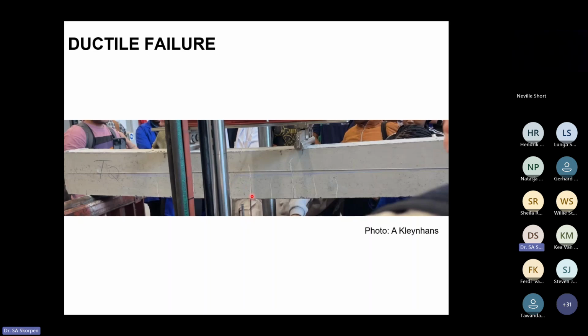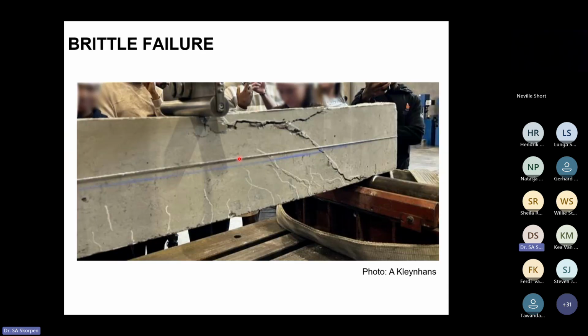And eventually the steel would start to yield, and the final failure would be when the concrete crushes over here. But if you had an over-reinforced beam, which has a brittle failure mode, now you can see much smaller cracks, and then all of a sudden this brittle failure where the concrete suddenly crushes, and that's your over-reinforced beam.